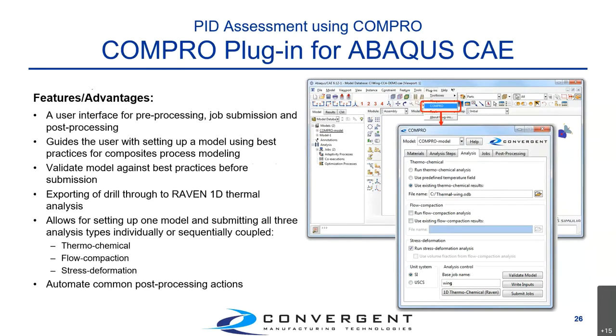If you have a complex geometry workflow with flow compaction and want to run to gelation before moving to the stress deformation step, you can quickly export a 1D drill-through section through part and tool, run it in Raven, and quickly see the evolution of resin viscosity to find exactly when gelation happens — so you can time the transition between steps precisely.